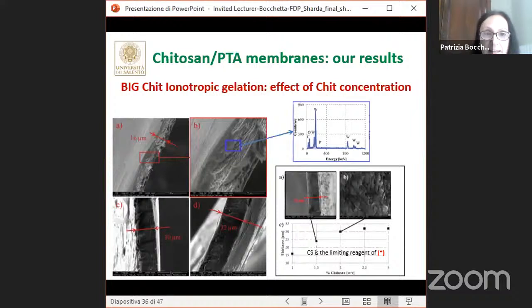Also, we can see that the thickness of the final film increases with increasing the concentration of chitosan solution. Also, by decreasing the concentration of acid, the mechanical properties of the final gel were not enough to self-sustain the membrane. So these results show that not all the acid anions are prone to cross-link chitosan, and also that cross-linking is essential to stabilize the mechanical stability of the polymer. So in order to investigate the effect of cross-linking, we have also made subsequent immersion of the membranes in a highly concentrated acid solution.